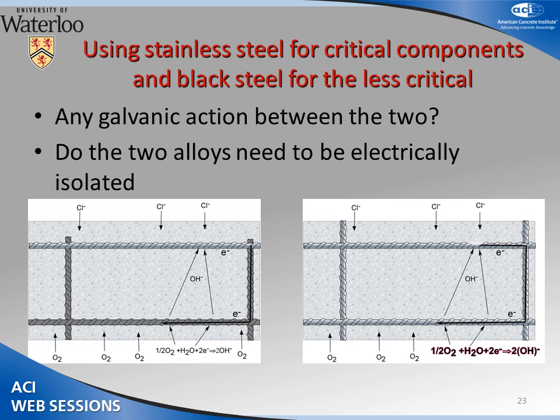And stainless steel has a much lower exchange current density. So the efficiency of this reaction on stainless steel is much less than it is on black steel. So if you connect black steel in a chloride environment to stainless steel in a non-chloride environment, the corrosion rate would actually be less than if you connected it to another piece of black steel in a non-chloride environment. And that has saved the authorities a huge amount of money. This experiment's since been repeated in Italy and various other places.